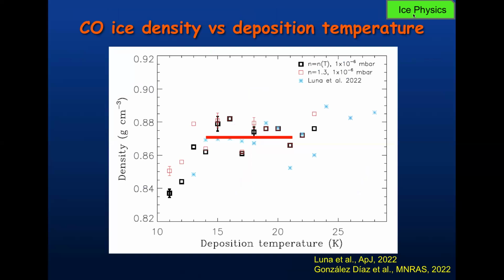About the density of the ice, you can estimate the density at different growth temperatures. So in the case of CO, you see this tendency: you have a plateau between 15 and 20K. You have an increase, which is due to crystallization. When the ice crystallizes, the density increases. And you see the opposite if you grow the ice at the lowest temperatures: the degree of disorder is also influencing the density of the ice. We have done this work in collaboration with the Alcoy group, with Satorres group.